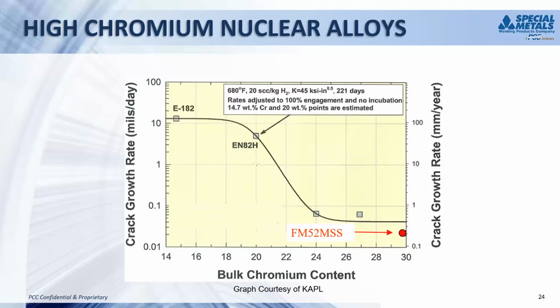One of the other big applications in the United States was the high chromium, 30-ish percent chromium nuclear alloys. Historically, a lot of the welds on the nuclear power systems in the United States were welded with an Inconel 82 or a 182 electrode, which is anywhere from about 14% chrome all the way up to maybe as high as about 20%. But that was still causing some problems with stress corrosion cracking down the line in these components.